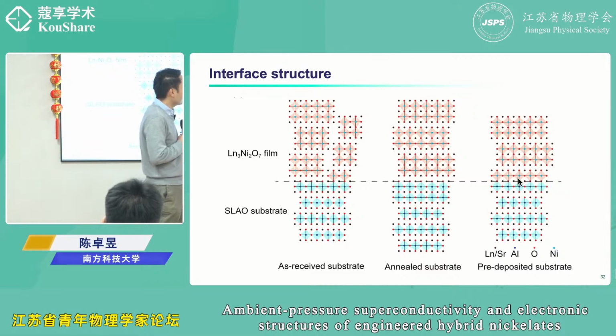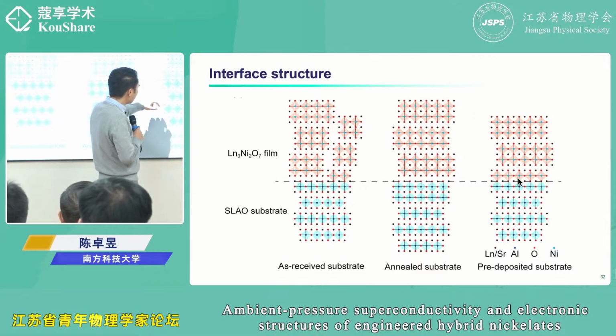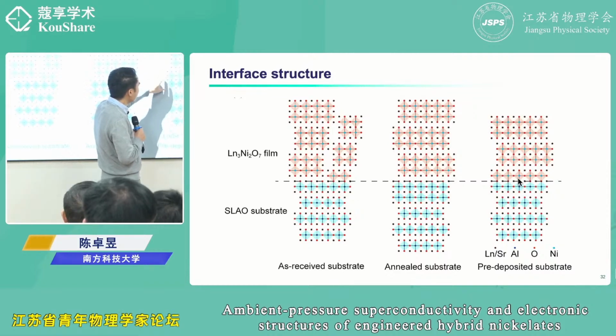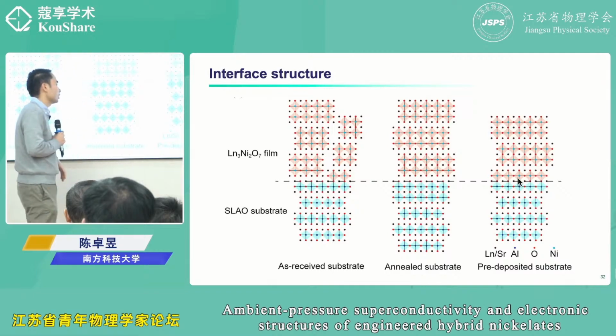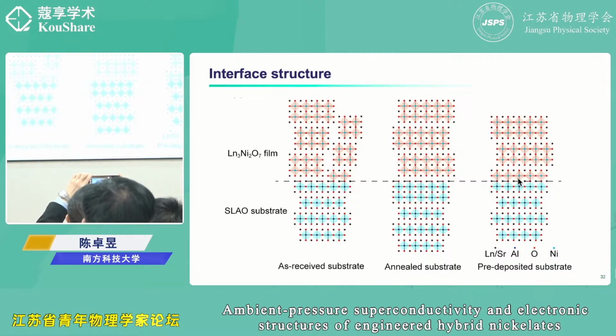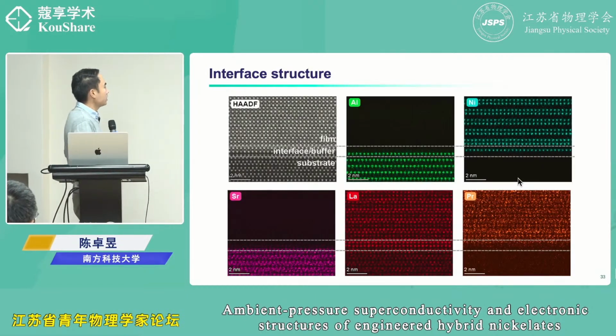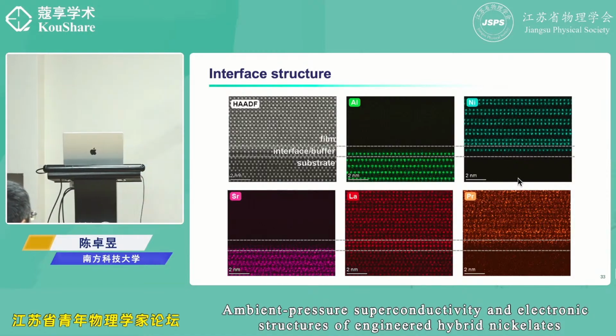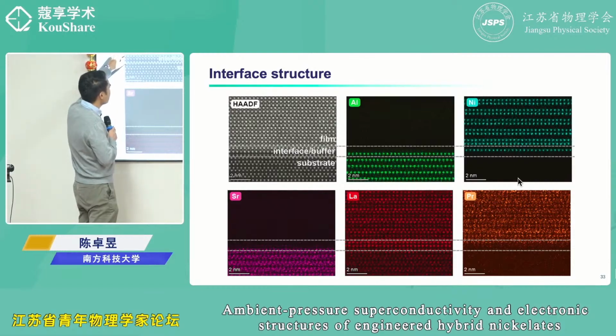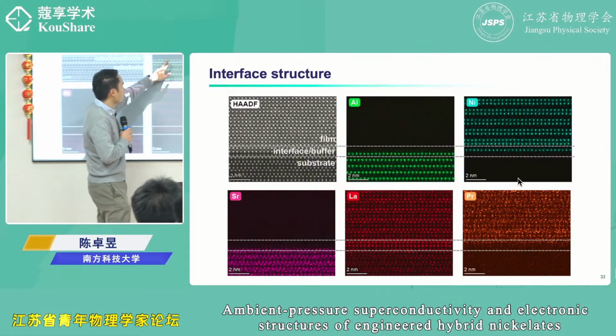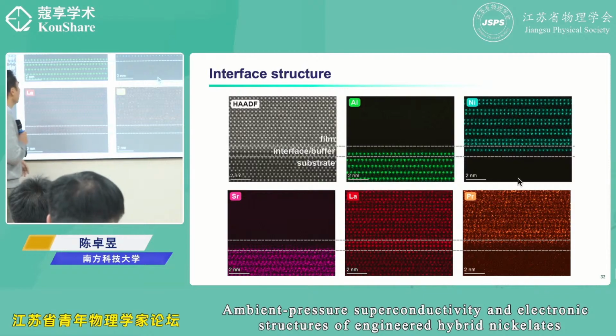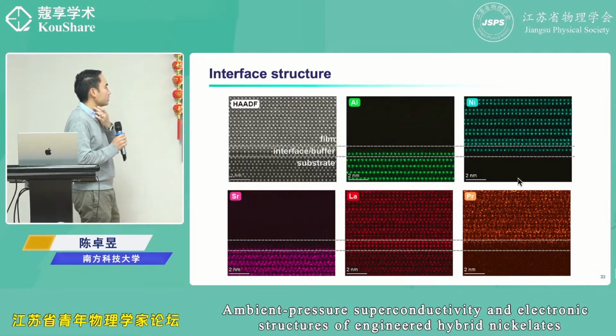So we use this new method: deliberately grow a monolayer first to form a nickel aluminum bilayer structure. This is a reconstructed interface, or you can also say a buffer layer. After this, you grow the bilayer, and it's pretty coherent on top. This can be clearly seen in the TEM. Underneath is the substrate, and this is the interface buffer. This bilayer you can see: the lower layer is aluminum, and the upper layer is nickel. So this is an aluminum nickel bilayer structure.